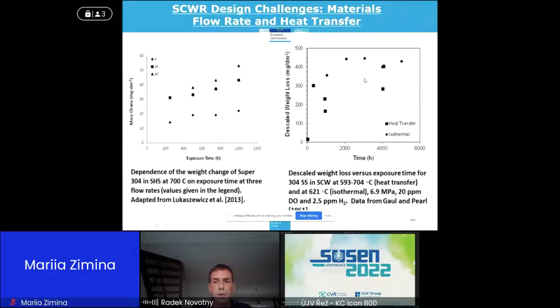There are a very limited number of studies on this topic. One of them is in this graph on the right side. We don't see any big effect of heat transfer in this case. Maybe we even see that in isothermal conditions, corrosion rates are a little bit higher. But anyway, this needs to be tested, and again, we need to prepare dedicated experimental facilities for it. When we talk about the flow rate, that's one of the few studies on the left side. The flow rate effect has clearly been demonstrated many times to have a big effect on corrosion rate, and we need to make dedicated tests to find out.